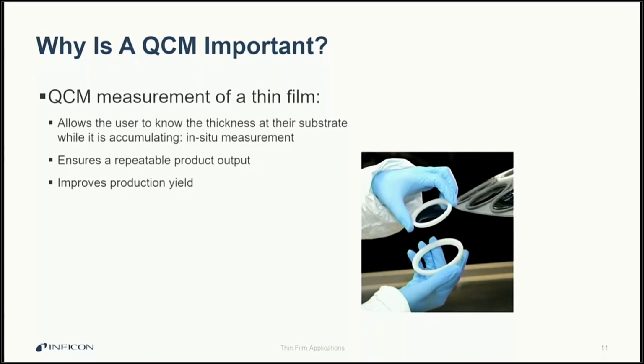In these applications, a QCM is an effective tool for measuring thin film thickness as a deposition takes place. This is known as an in situ measurement, and a QCM is able to provide in situ measurements of a thin film because the QCM sensor and the substrate are both coated by the source material at the same time.